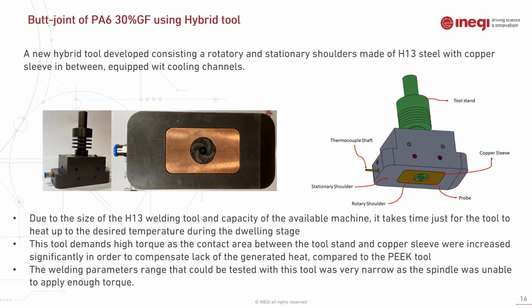Also, this tool demands high torque as the contact area between the tool and copper sleeve were increased significantly in order to compensate lack of the generated heat when compared to the PEEK tool. The welding parameter range that could be tested with this tool and the available machine was very narrow, as the spindle was unable to apply enough torque.